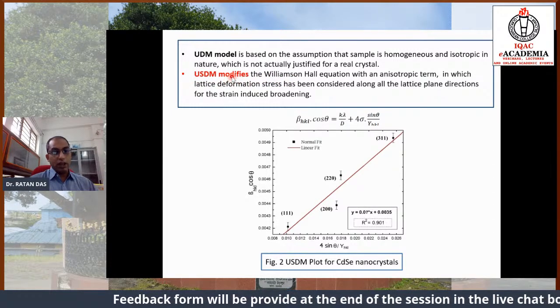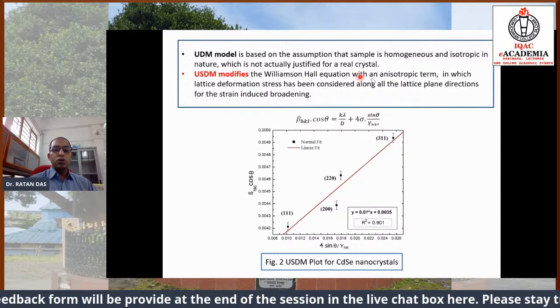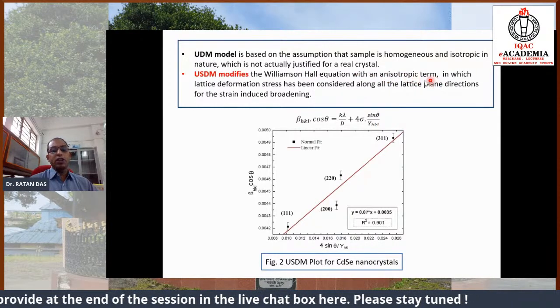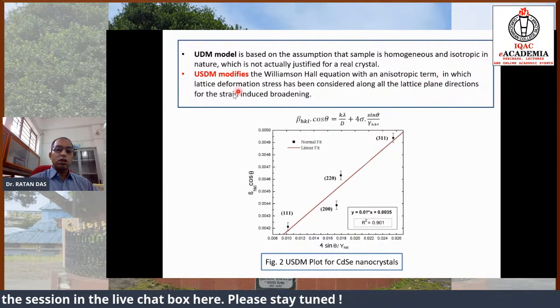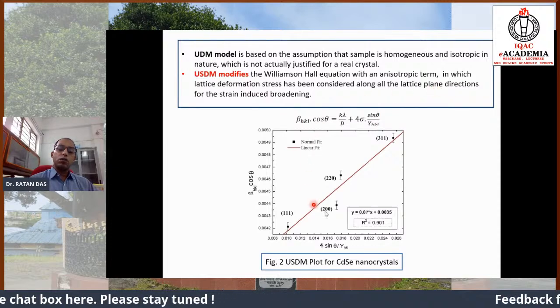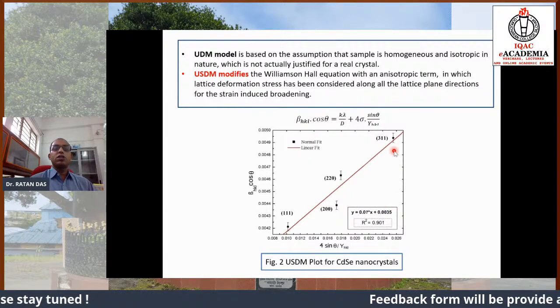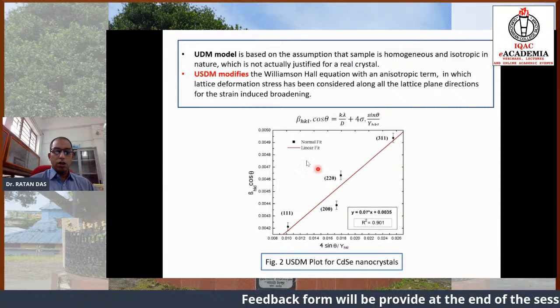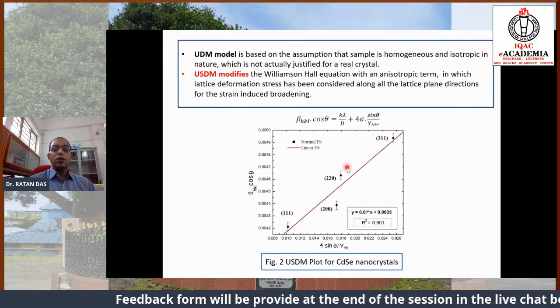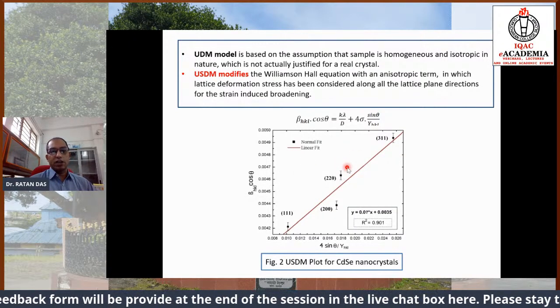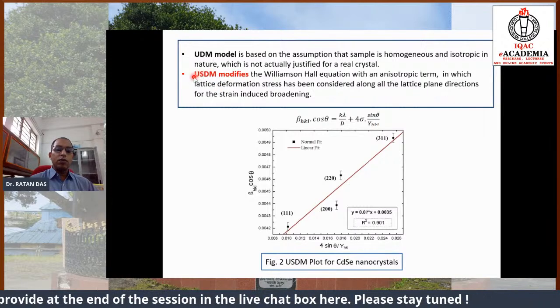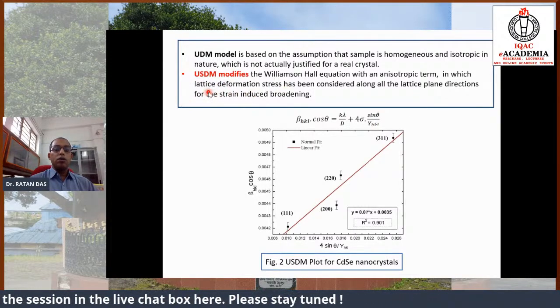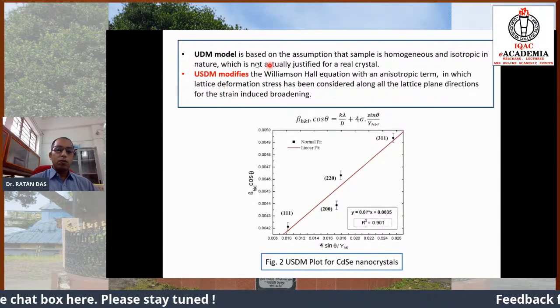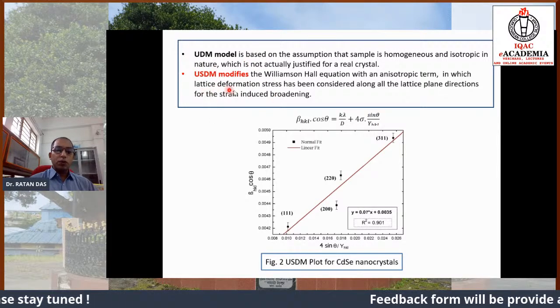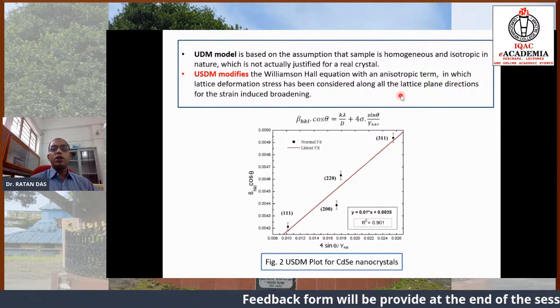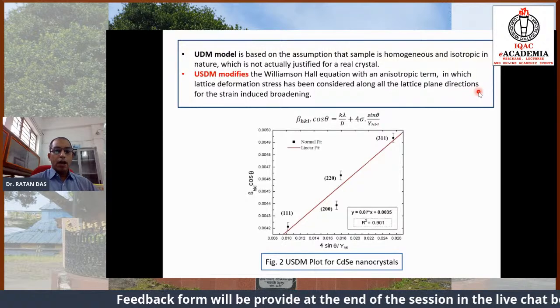This modifies into another model which uses the anisotropic term. Anisotropic term means it does not use the uniform strain in every crystallographic direction. It considers that there is some non-uniform strain in every crystallographic direction. And this uniform stress deformation model considers some stress deformation in every crystallographic plane.